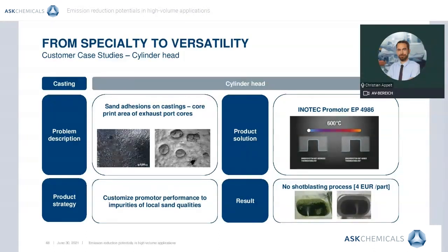A predominant problem in the production of cylinder head castings using inorganic binder systems is the appearance of sand adhesions and penetrations after raw part machining, especially on the core print areas of port cores. This defect is described by the partial appearance of sand grains on the casting surface due to the mechanical penetration of the liquid aluminum melt into the sand core surface, or the electrostatic adhesion of sand grains on the casting surface itself. Casting parameters, for example casting temperature and pressure, have an influence, but customers are seeking a chemical binder system solution that withdraws the need for intensive process control and casting rework by shot blasting.